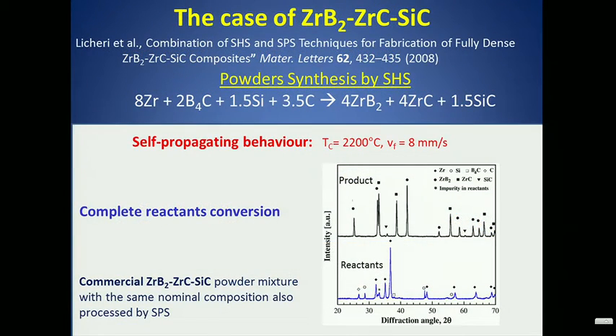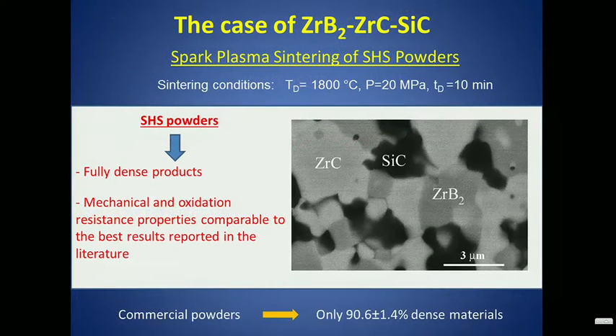So let us consider now a couple of cases, then I can skip if I am out of time. Let's talk first about this complex system here, the zirconium diboride, zirconium carbide, silicon carbide system. You prepare the powders by SHS through this reaction. Then, of course, you can see that you get the complete conversion. And then you process them by SPS.